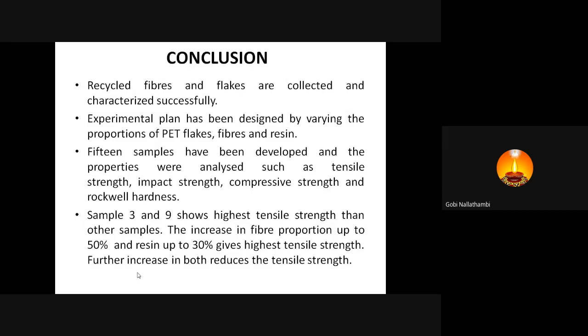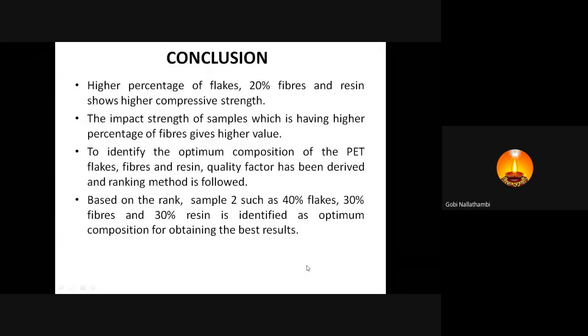The increase in fiber proportion up to 50% and resin up to 30% gives the highest tensile strength. So this is the finding, that usage of fibers up to 50% can give better performance. Further increase will lead to a decrease in performance with respect to tensile property. A higher percentage of flakes, with 20% fibers and resin, shows higher compressive strength. The impact strength of samples with a higher percentage of fibers gives higher values.